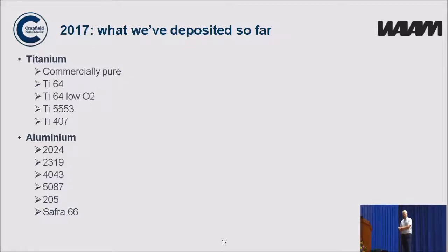For aluminium alloys, we've looked at a range of 2000 series, 2024, 2319, 205, some 5000 series, 5087, Safra 66, 5566, and also aluminium silicon. Of course, aluminium alloys are much more challenging than titanium alloys because they are heat treatable, or most of them are, the high strength ones.